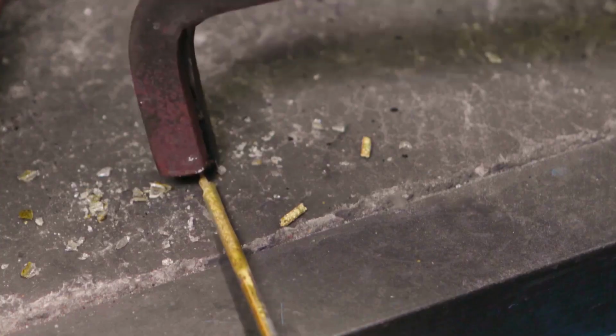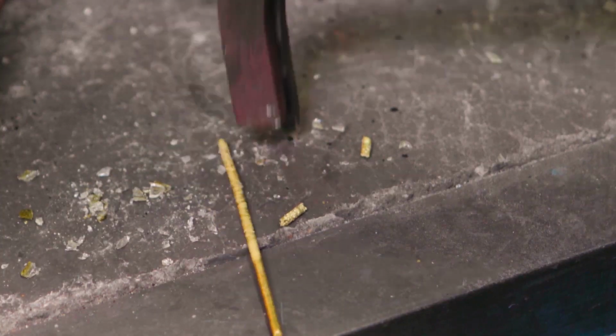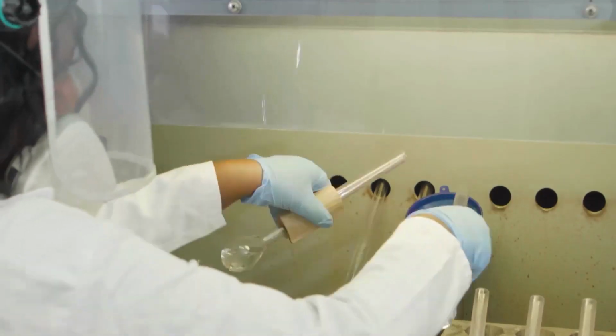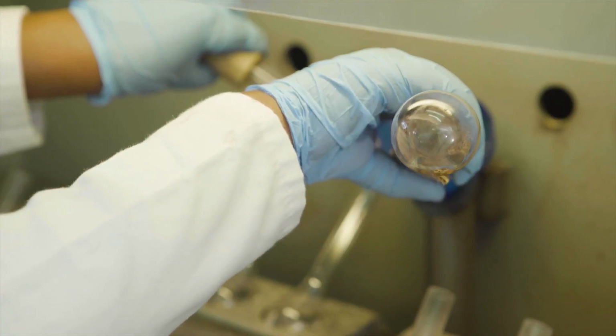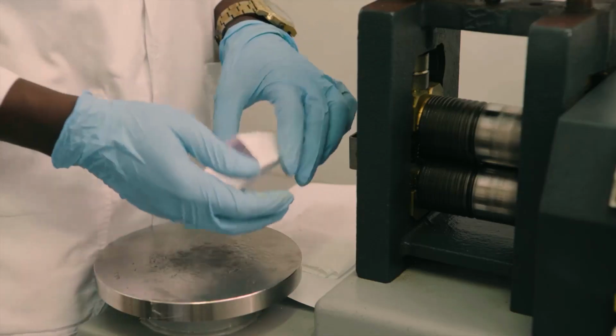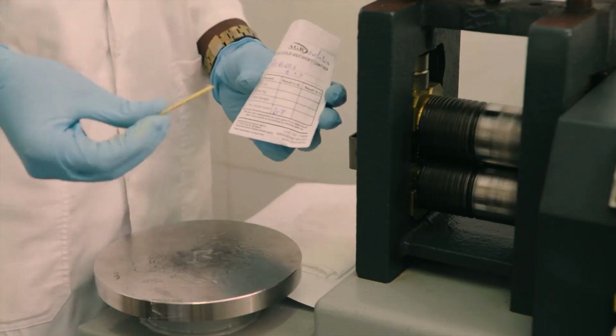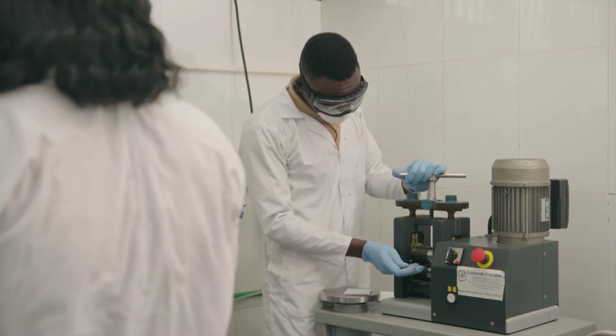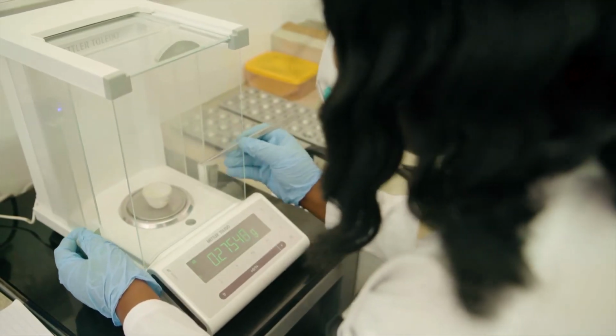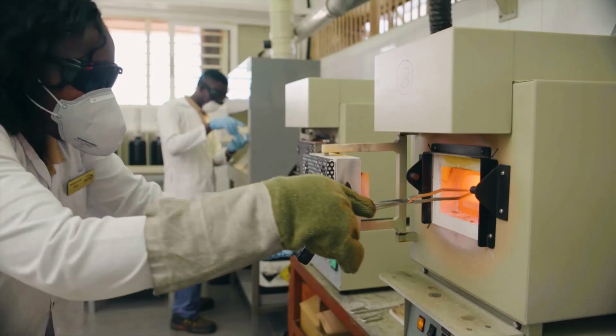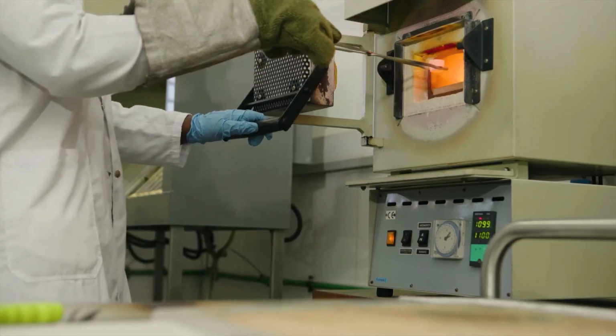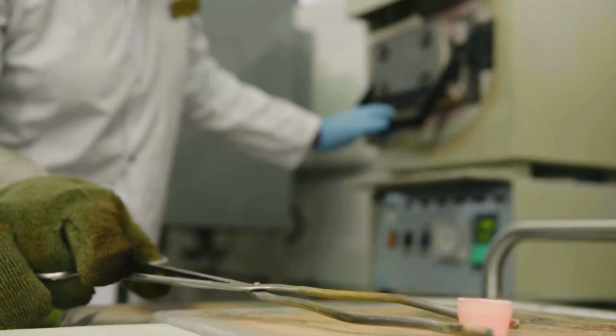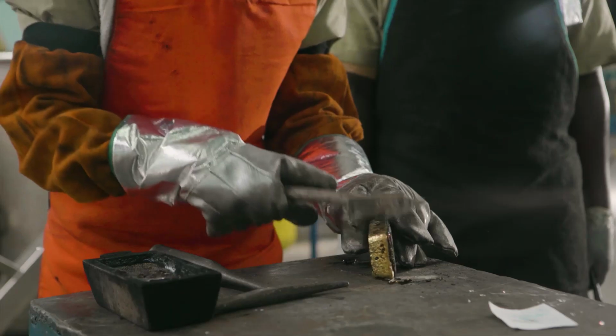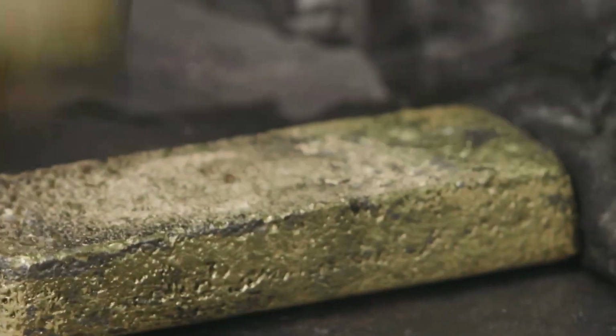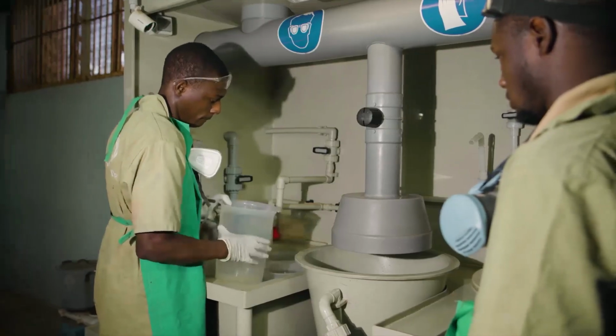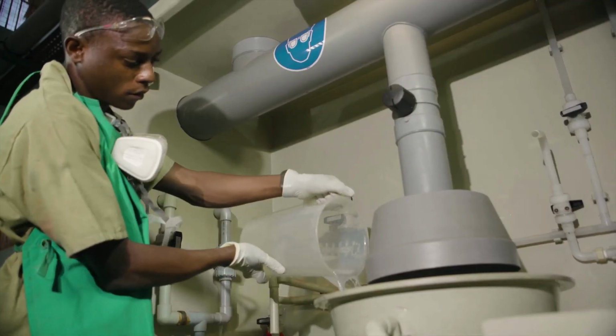When the refining is completed, the gold is placed in a granulator, through which it is made into small granules for weighing. Place the gold granules in the bar mold, and finally place the mold in a vacuum bar casting machine. Under the protection of vacuum and inert gas, it can avoid gold oxidation, shrinkage, and water ripples on the surface. After casting, place the gold bars under the logo stamping machine to press out the required patterns and text. Then use a dot pin marking machine to number the gold bars.